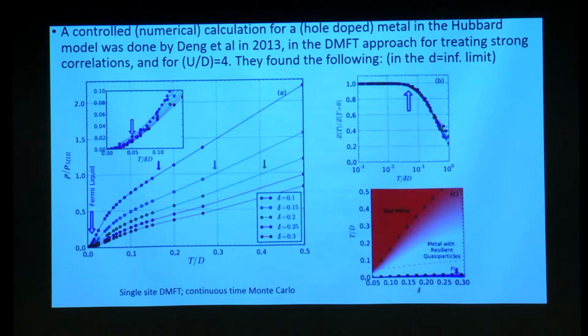Okay. Now this has been an observation for a long time. This is not new. There has been a lot of effort to understand this. One such effort is a numerical calculation for a hole-doped metal in the Hubbard model, which was done by a number of people, including Kotliar and Georges, using the dynamical mean field theory for treating strong correlations in a strongly correlated metal. And what they did find was that the resistivity in dimensionless units of the Mott-Ioffe-Regel limit increases not quite linearly at very low temperatures, but then increases linearly at higher temperatures.